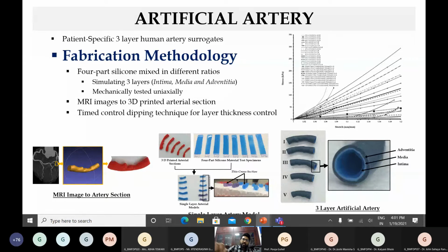different times of dipping. So what happens if you dip at 5 minutes? What happens if you dip at 10 minutes? What happens if you dip at 15 minutes? We found out a specific time. If we dip after that much time of mixing of our composition, the composition becomes viscous enough that you can get that layer thickness. So this was very laborious work, which took a while, and we finally found out that these are the times. This is called the time controlled dipping technique, using specific material compositions through which we can achieve the 3 layers over this lumen 3D printed model.